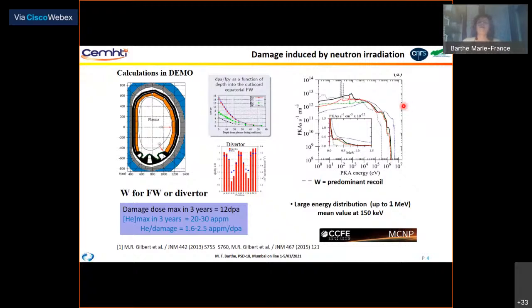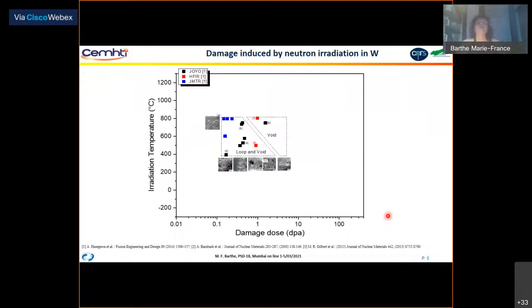We can see on the right here the PKA energy distribution. Of course, tungsten is the predominant recoil in tungsten, and the PKA distribution is large and can go up to 1 MeV with a mean value of about 150 keV. So damage has also been studied by using TEM in tungsten which has been irradiated in different neutron reactors, that means fission reactors.